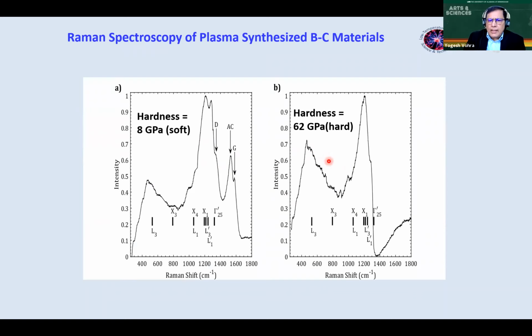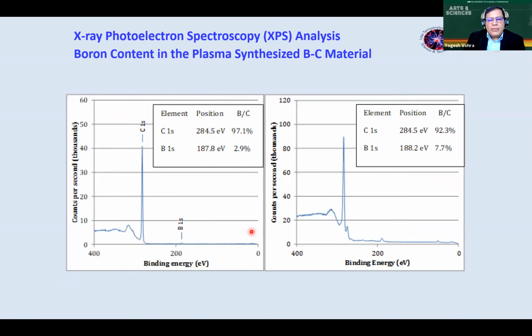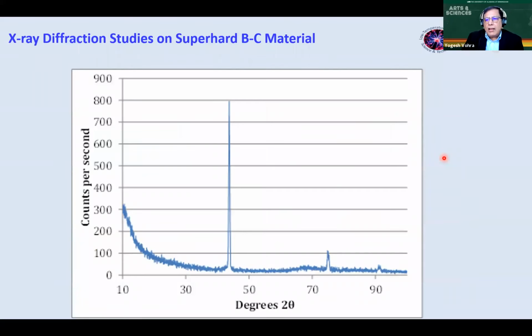So then we went and directly measured what is the boron content in these films. There's a technique called X-ray photoelectron spectroscopy. And what it showed was that the soft material has a boron concentration of 2.9%, and the hard material has a boron content of 7.7%. So we concluded that 7.7% is almost the maximum boron you can put in the diamond lattice. In fact, our X-ray diffraction just showed us the diamond structure and nothing else.